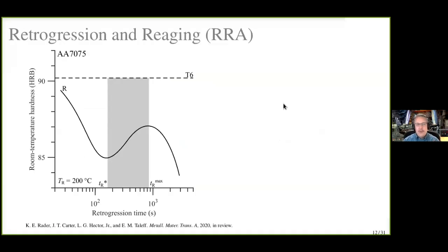Okay, retrogression and reaging. Retrogression and reaging is a particular heat treatment first applied by Cina. He had a patent on this. It was applied particularly to 7075. The goal of this heat treatment is to improve the stress corrosion cracking resistance of 7075. These high strength aluminum alloys are a bit prone to stress corrosion cracking problems.